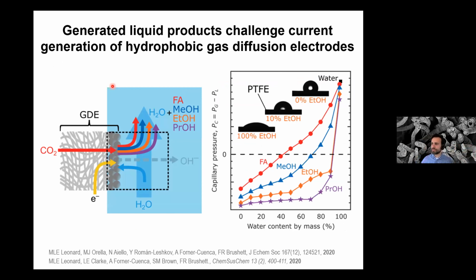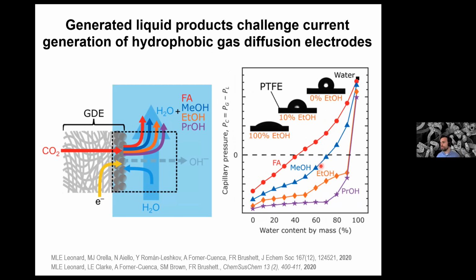But now when you move to CO2 electrolyzers, and particularly if you are interested in producing organic products, so think about formic acid, methanol, ethanol, propanol, all these materials have much lower surface tension than water. And as a consequence, the contact angle and the capillary pressure characteristic will change. And here we wrote a paper a few months ago where we tried to highlight that problem, which is, what is your operational envelope that allows you to produce a certain product without flooding a gas diffusion electrode, at least a current generation gas diffusion electrode. And you can see that your window is pretty narrow, particularly when you move to these higher carbon atom alcohols like propanol, where with very tiny concentrations of propanol in water, you would already break through and flood your gas diffusion electrode.